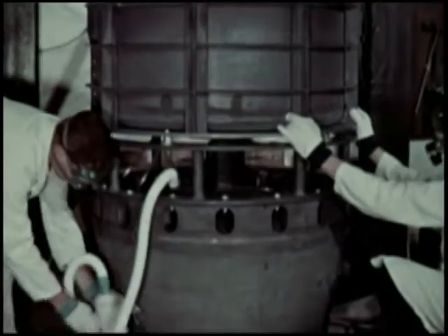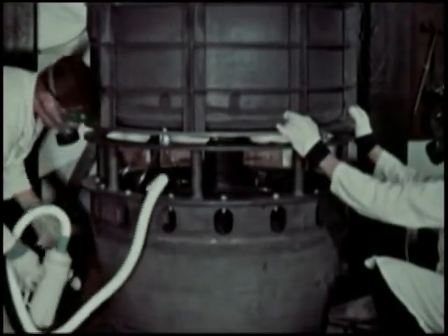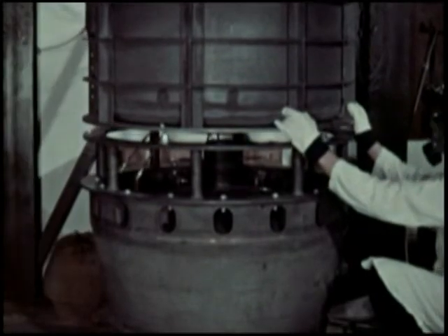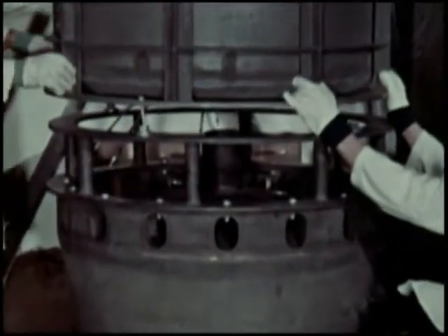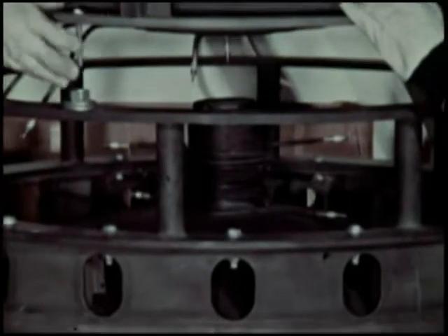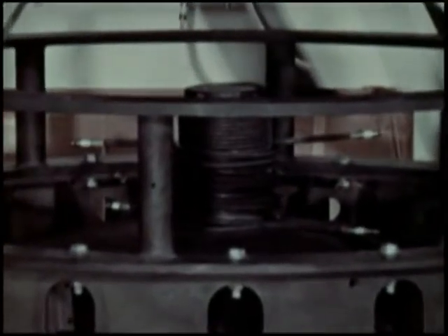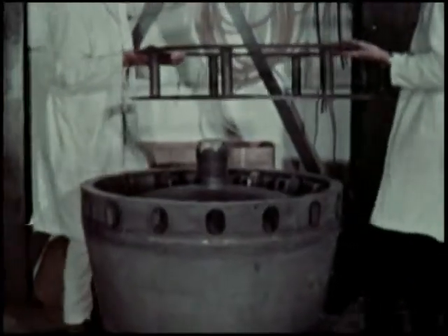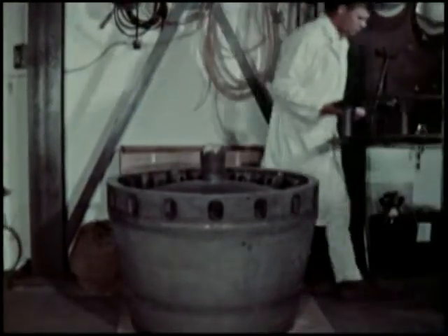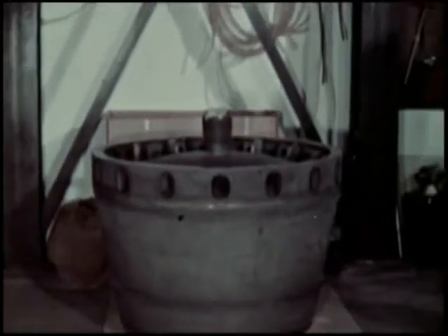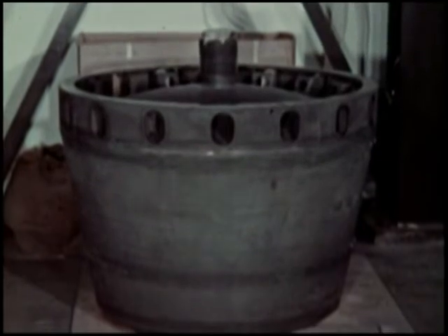This should attenuate SNAP-8 reactor radiation to a total neutron dose of 10^13 NVT fast neutrons and the total gamma radiation dose to 10^7 rad at a payload 8 feet in diameter located 15 feet from the reactor. This shield weight is 1,100 pounds.